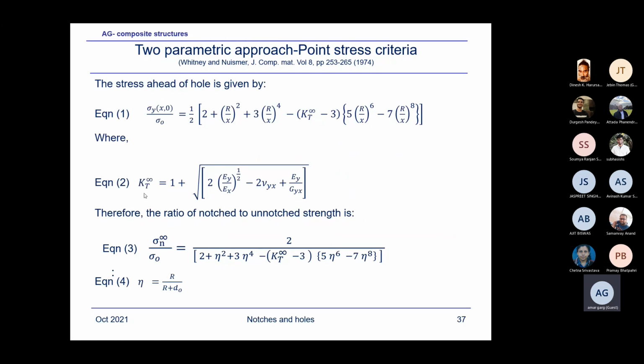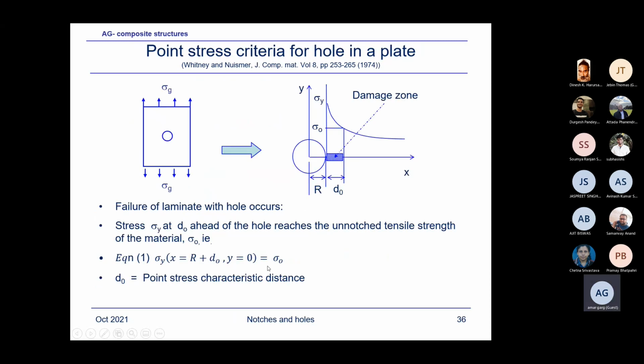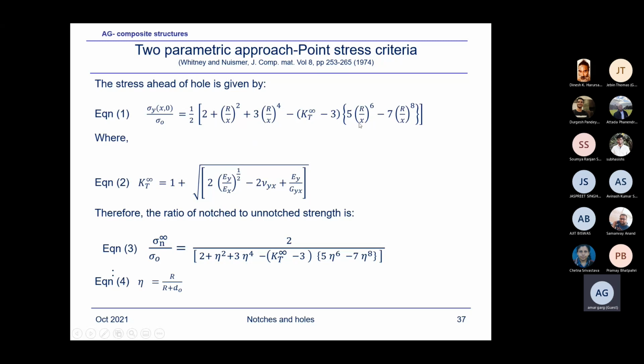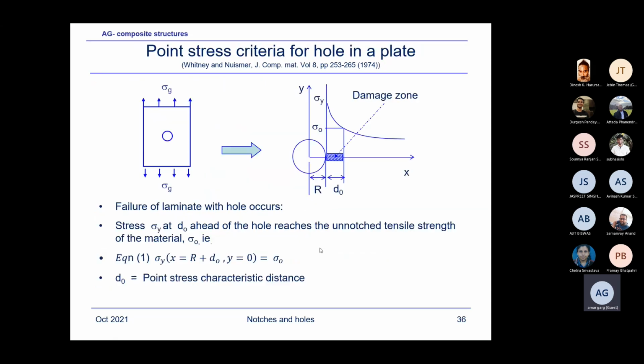Now we had written down this expression, sigma y upon sigma naught. This is the stress distribution. And that means when the failure occurs, when x is equal to r plus d naught, if we substitute here, instead of x, r plus d naught, and solve this equation, that will give this equation, sigma n infinity. We are providing the infinity letter because it is for an infinite plate. And if it's a finite plate, in terms of the width of the plate compared to the hole, the functionality of that, we call the finite width correction factor, which will apply.